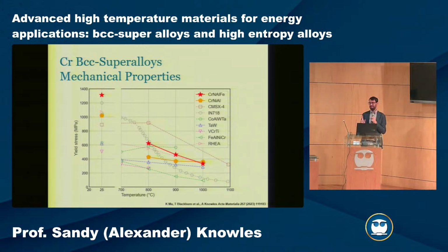We're not yet there in terms of the balance of properties. Within these things, we get good strength, we get good oxidation resistance, we get good corrosion resistance, but we don't yet get ductility. And this is one of the major challenges for BCC superalloys, for BCC alloys, and for intermetallics, is trying to get this combination. You can improve the strength, but do you do it at the cost of ductility?